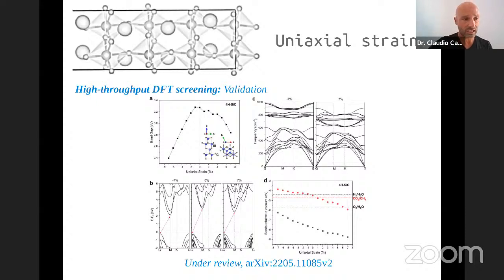We did the same for silicon carbide. Silicon carbide is very interesting because it has many different polymorphs. Some of them are piezoelectric, some others are not, so we can compare very meaningfully how the band alignments evolve under uniaxial strain. Do not forget that our main motivation for this work was to see whether we could have materials in which the evolution of the band alignments could be systematically and rationally predicted. We found that in this case also the modeling we did was meaningful and compatible with our explicit DFT calculations for the band alignments.